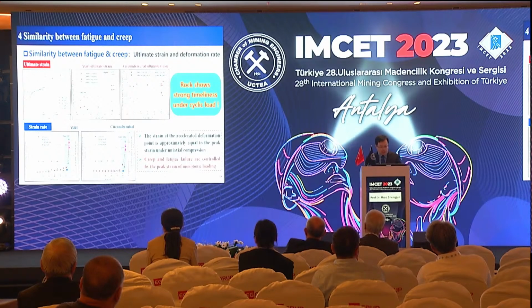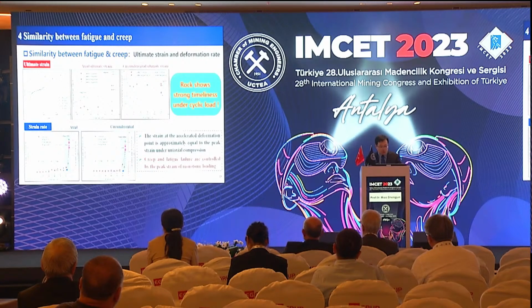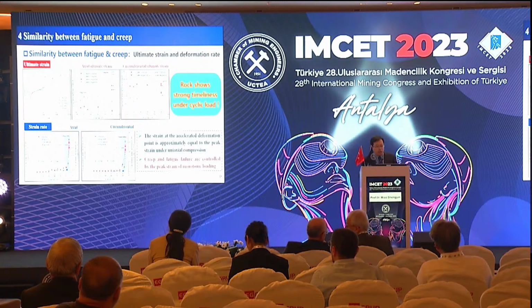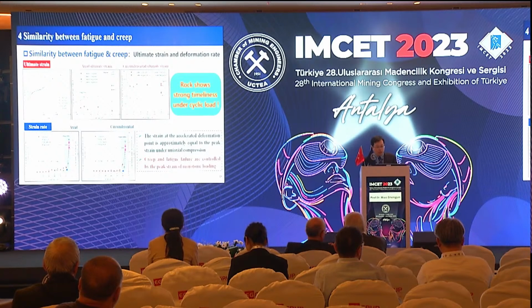We found that the strain at point A is approximately equal to the peak strain in uniaxial compression. In other words, under the cyclic load test, the limit of axial strain is the uniaxial compression peak strain. Furthermore, we found that the deformation rate under cyclic loading can reach 5,000 to 7,000 times that of the creep deformation rate, showing significant time-dependent behavior. However, regardless of how fast the fatigue deformation rate is, it is still controlled by the peak strain of the static loading test.